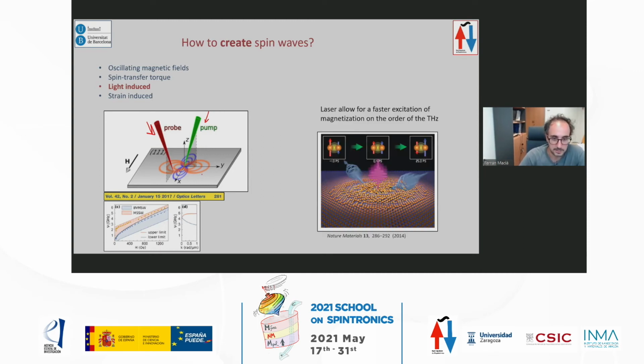In this article, they saw that the dispersion relation followed the theory when it propagates in the direction of the applied field or in the direction perpendicular to the applied field. What's interesting from light-induced spin waves is that this only works in certain materials. In fact, they have to be ferrimagnets. Ferrimagnets means that you have two lattices, one with the spins in one direction and another with the opposite direction, with a smaller magnetization. And the way it acts is completely different.